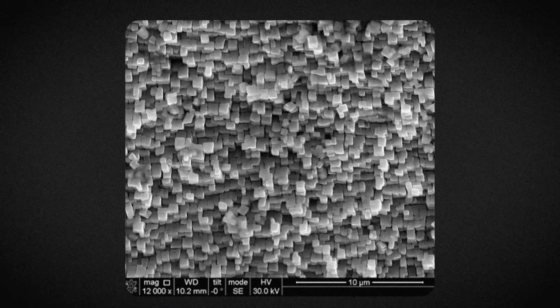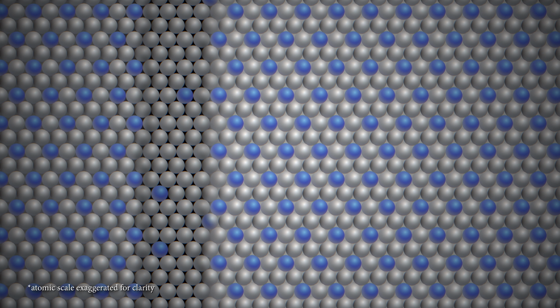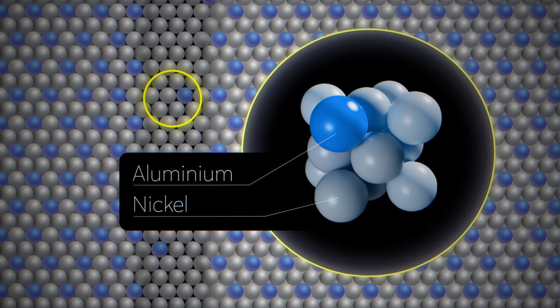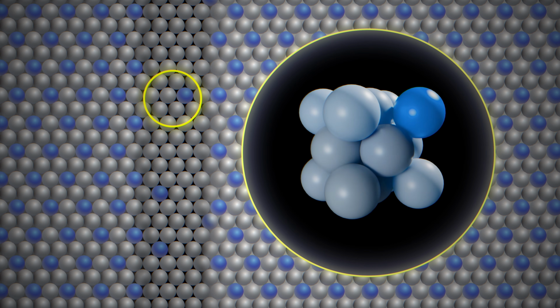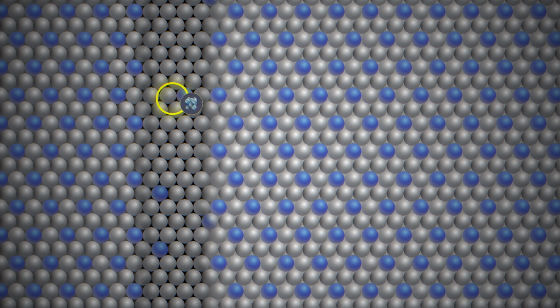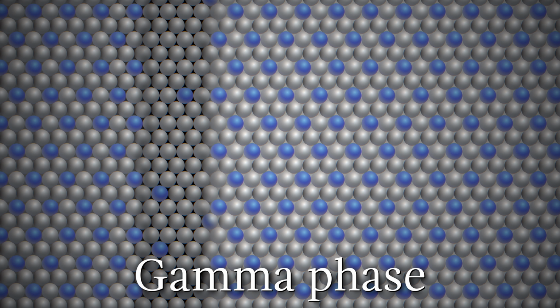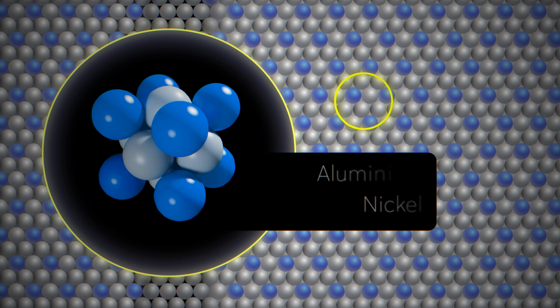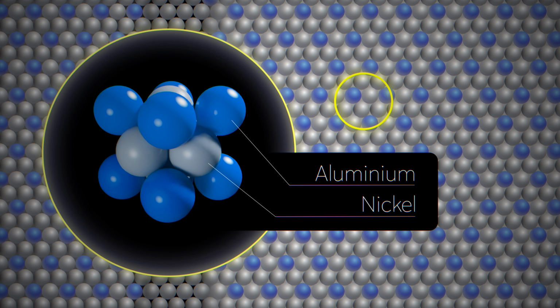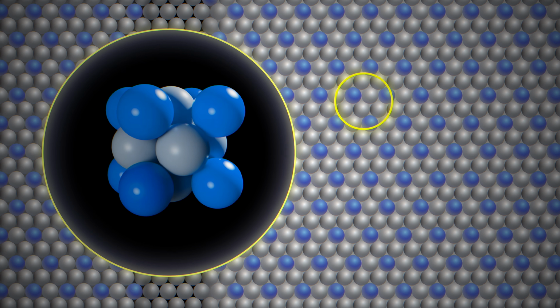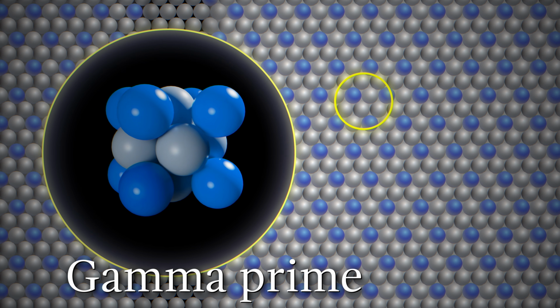Now, surprisingly, both the roads and the blocks are made up of the exact same atoms, mostly nickel with a little aluminum. They even have the same crystal structure, a grid of tiny cubes with atoms sitting at the corners and at the center of each face. The only difference is that the atoms are arranged slightly differently. In the road structure, the aluminum and nickel can take any spot. There is no repeating sequence from cube to cube, and this is known as the gamma phase. But in the blocks, aluminum always takes the corner spots and nickel the faces. And you get a perfect repeating pattern cube after cube. This is the gamma prime phase.